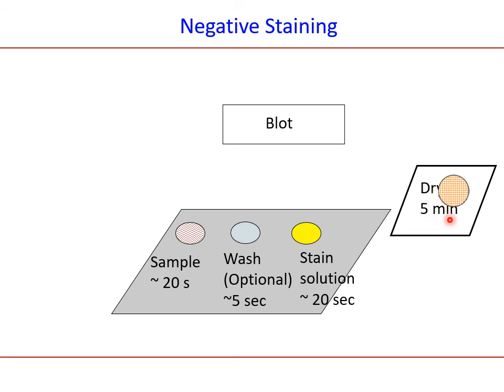One precaution: longer time on the sample causes aggregation or too many molecules adhering to the copper grid surface. Too little time means fewer molecules. This depends on the concentration of your starting material — if the protein is more concentrated, less incubation time is needed; if less concentrated, a relatively longer time can be used. The suggested 20 seconds is only a guideline; you have to decide based on protein concentration.